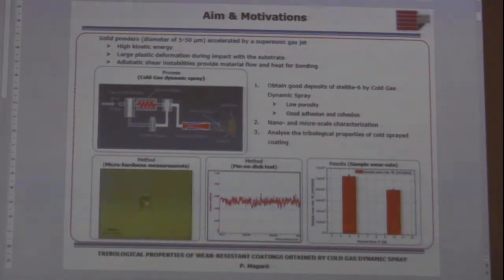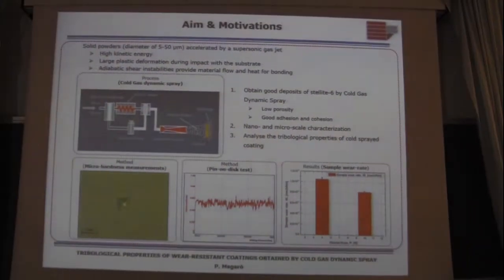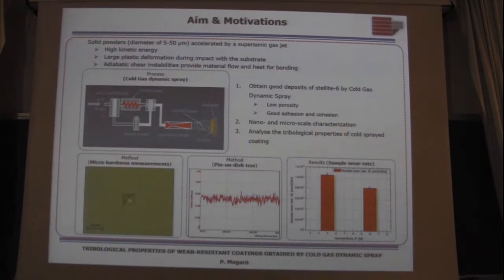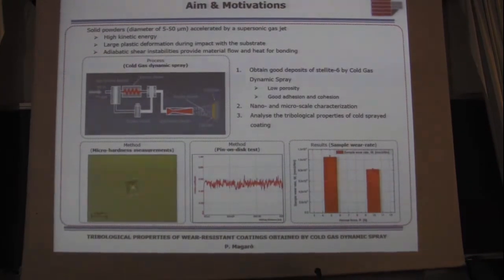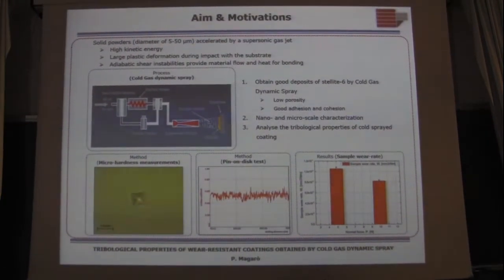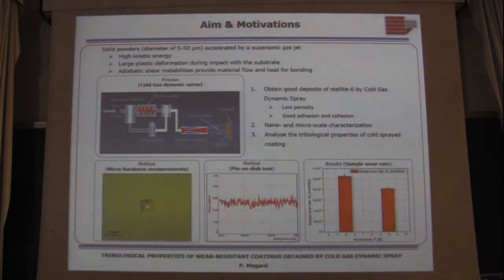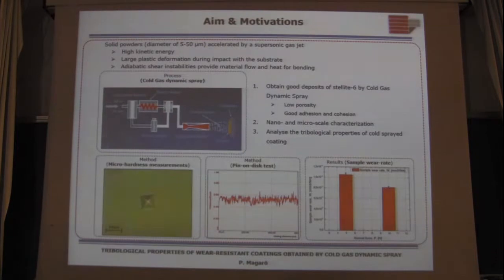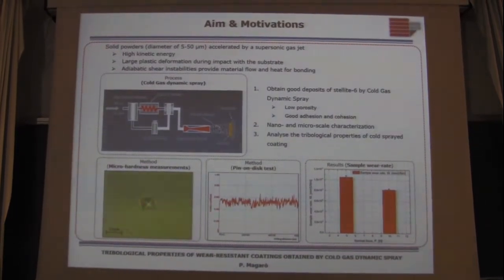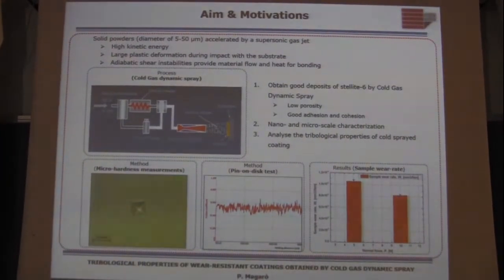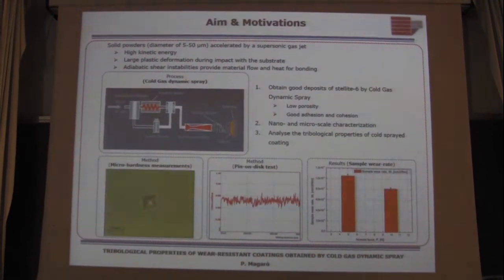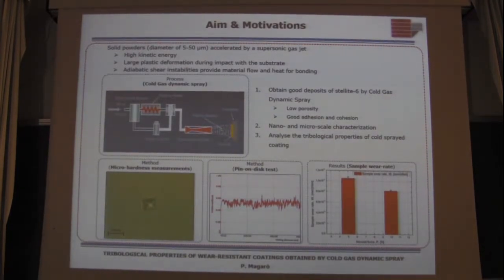Cold gas dynamic spray is a new, recent coating deposition technology in which very small particles, with a diameter of around 5 to 50 microns, are accelerated by a supersonic gas jet, in general nitrogen or helium. So the particles undergo large plastic deformation, and consequently adiabatic shear instability leads to the friction and the flow of material for bonding of the particles on the substrate.